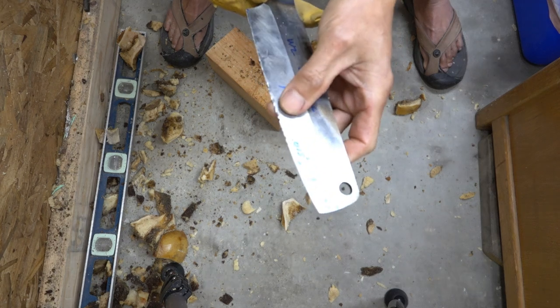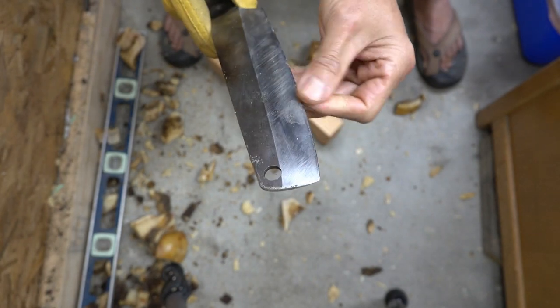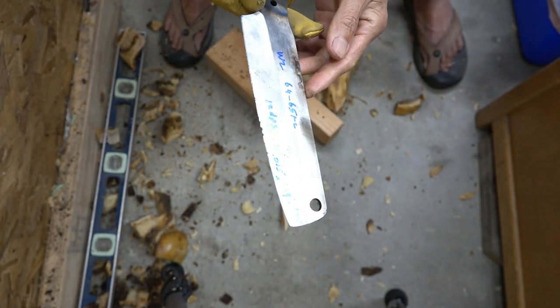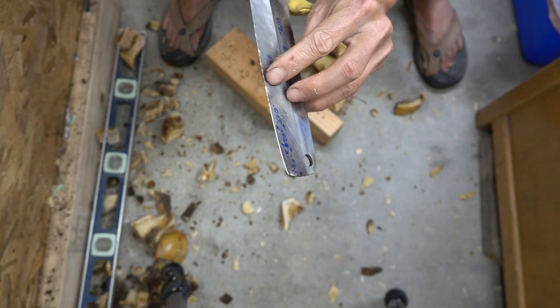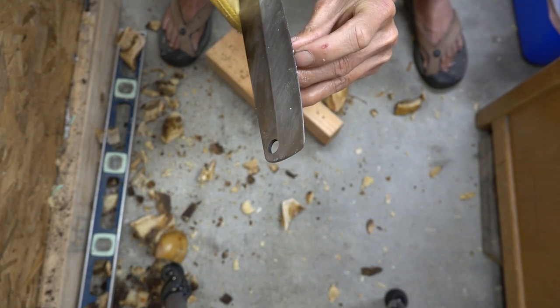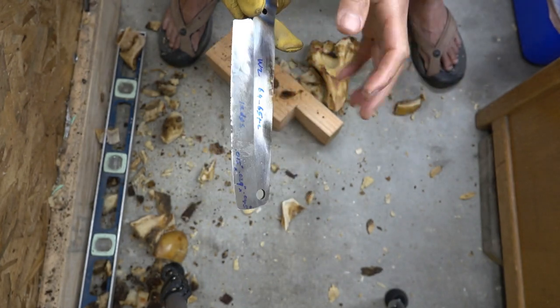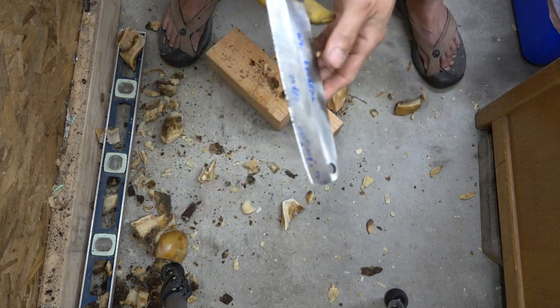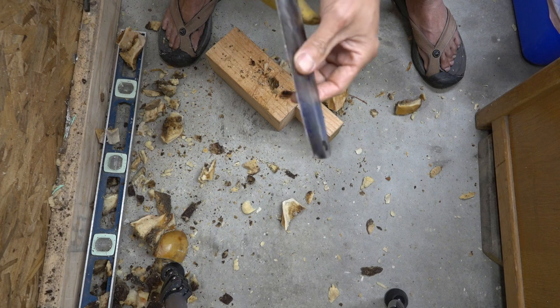I think these are rolling — and they roll really far, way too much. This is, again, 64-plus Rockwell hardness. So I think when it bends far enough, it would then chip away. Even if the steel is really soft — like an anvil — you can mushroom over a certain amount, but beyond that it will fall off, when it can no longer neck or stretch any further. And as you can see here, it's just a massive deformation. That piece fell off right there.